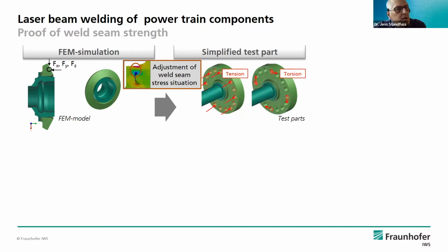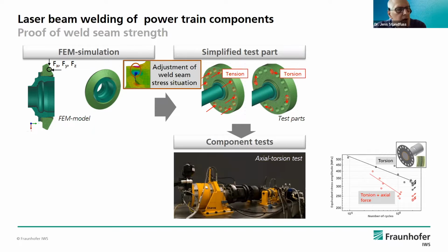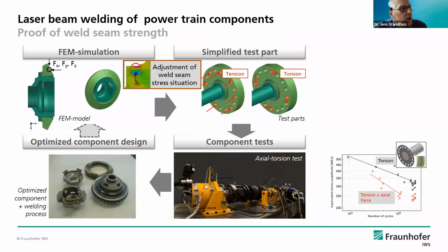But there are no dimension values for this special material combination. So you need some tests to get design values for the weld seams themselves. So it's a complex loading. You have some tension, you have some torsion, and we can do this in such a way that we use simplified test parts, but with the request that we have the stress situation according to the real part. We can test this by axial and torsional loading and get some stress strain curves for the dimensioning, and then we can optimize the component design also with the knowledge of the process itself. And at the end of the day, what is the advantage?